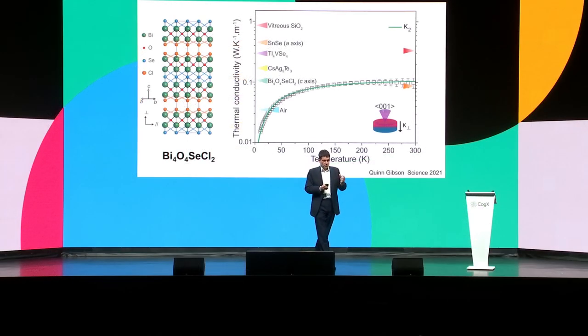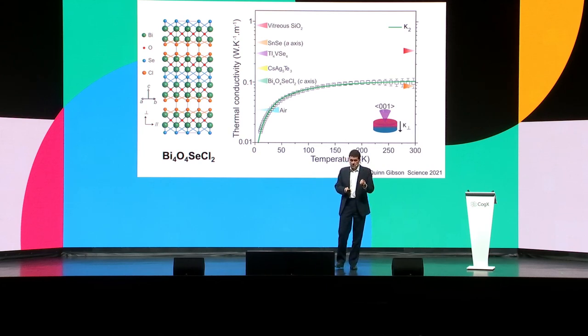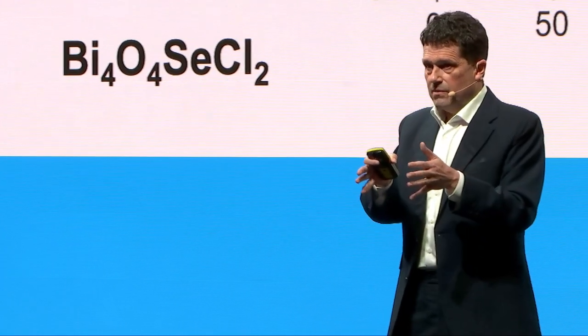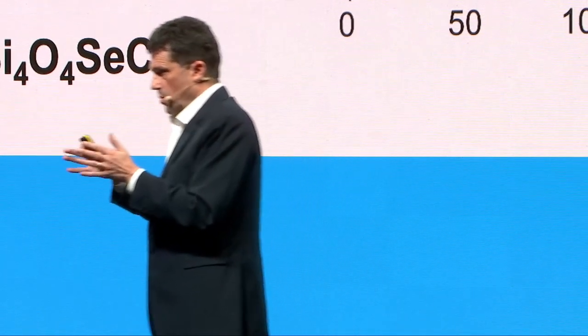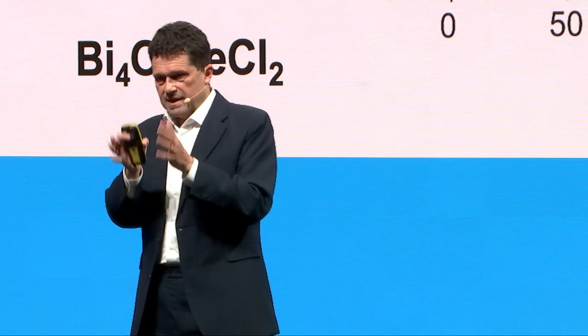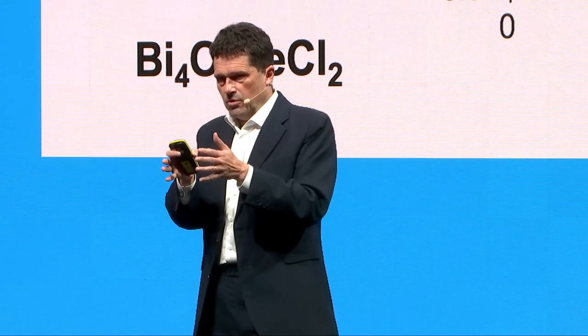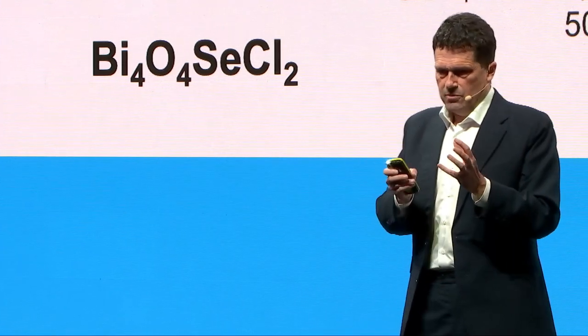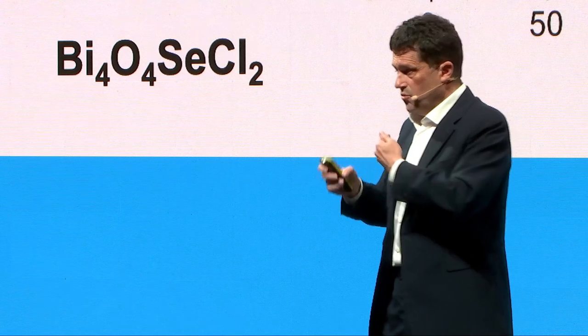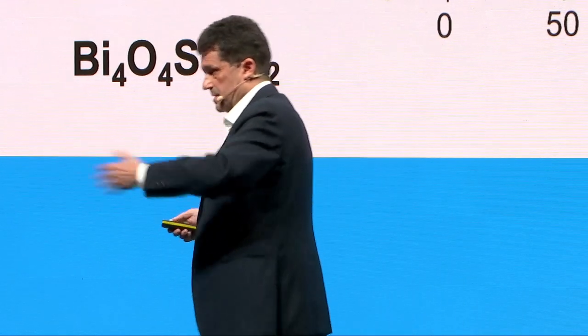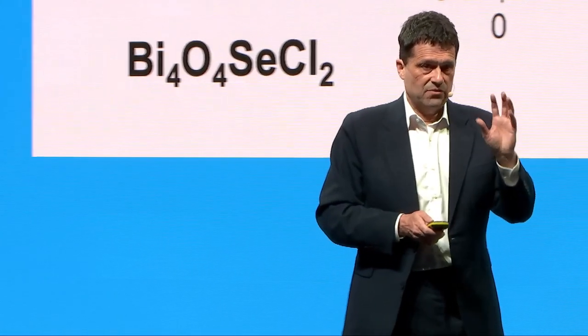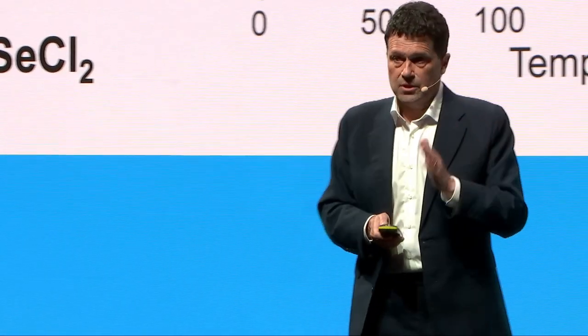Its thermal conductivity — and remember this is a dense solid — is only four times higher than that of thin air. Through our understanding of chemical bonding and crystal structure, we selected those elements because our insight was that this would generate a unique arrangement of chemical environments that would interact to generate vibrations within the solid that move particularly slowly. It is the motion of vibrations that transmits heat, and that unique, previously unseen combination of chemical bonding drives the low thermal conductivity.